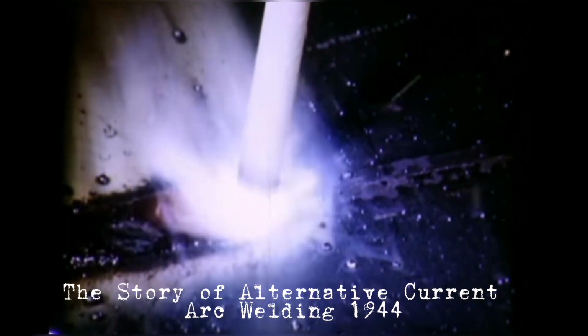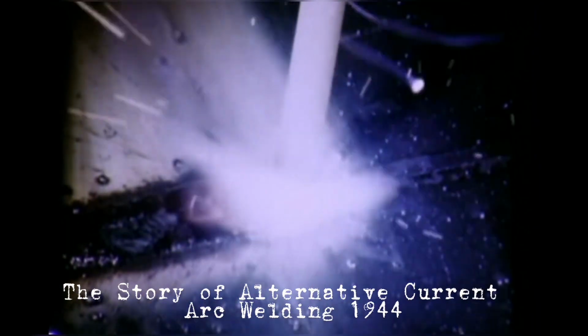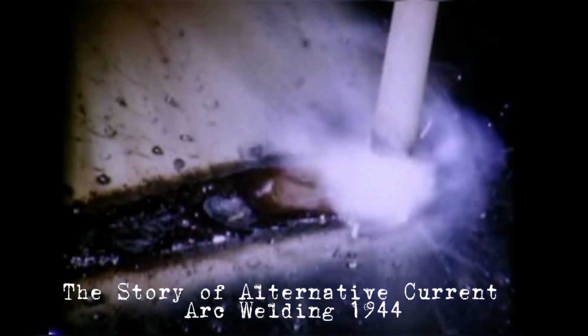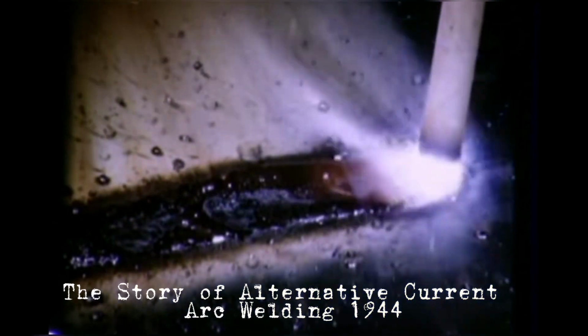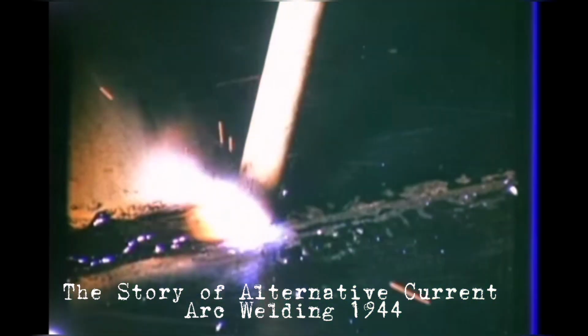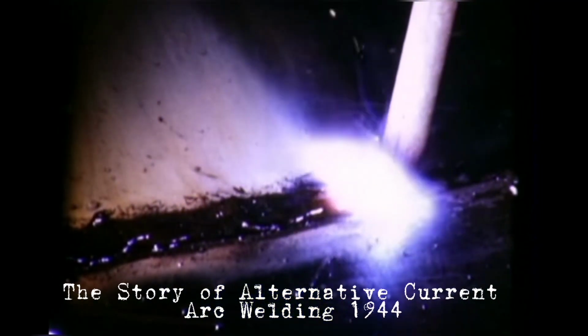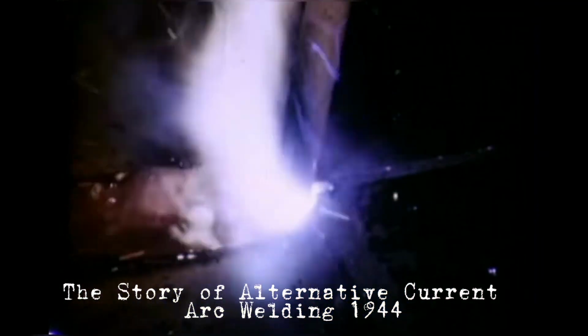When the correct current is used, and the other factors are also correct, the molten metal flows evenly to the rear of the pool, forming a smooth, uniform bead. Too low a current makes the bead high and narrow with poor fusion, while too high a current results in a wide, unruly molten pool with excessive spatter.